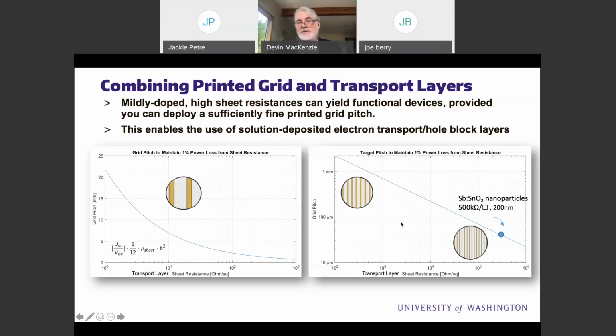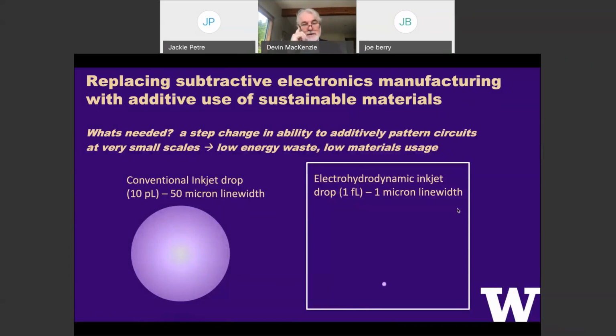For example, say an antimony tin oxide, 500 kilo-ohms per square, very mildly doped, we actually get this to 1% power loss from sheet resistance, and it's possible. Of course, this is all hand-waving possible. So how do we make that a reality?